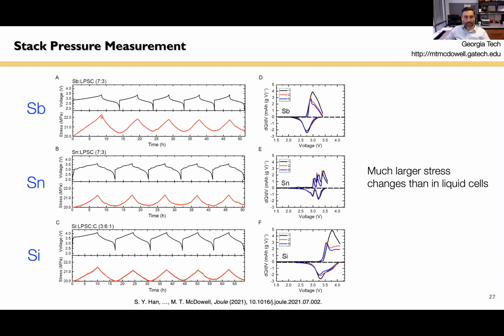This is also important because it's thought that for a commercial solid-state battery, you really do need low stack pressure on the order of 1 megapascal or less. So here we're showing that the change of stack pressure, and I'm going to show you that this is due to just the transformations of the materials inside, fundamental intrinsic transformations, this change in stack pressure is on the order of what you need the applied stack pressure to be.